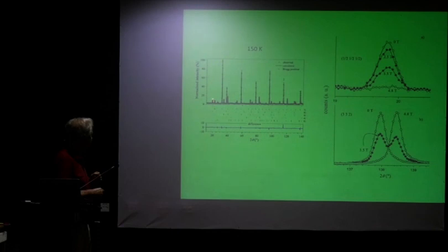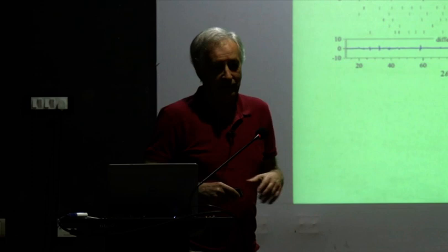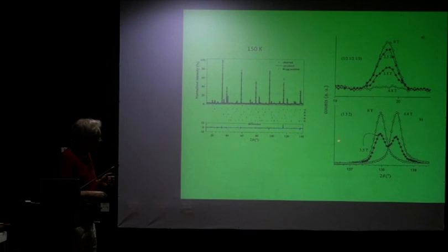So it's this one over here. Okay? This is a magnetic peak. It tells us that this thing is antiferromagnetic. So this is now beyond doubt that it is an antiferromagnet. And then we look at the 332 peak, which sits at around 138 degrees. So it's this one over here.